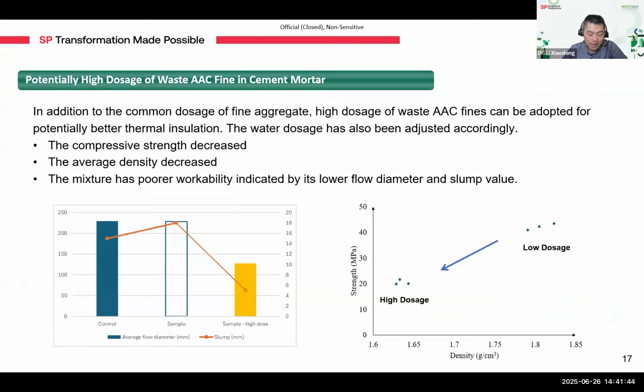So to better understand the limits and the flexibility of AAC usage, we also experimented with higher dosage levels, with a higher AAC to cement ratio. The water dosage was also optimized to compensate for the porous nature of the AAC, ensuring proper hydration and mix consistency. The compressive strength and the density both decreased with the higher AAC content, and the workability also dropped, as shown by the lower flow diameter and slump values.